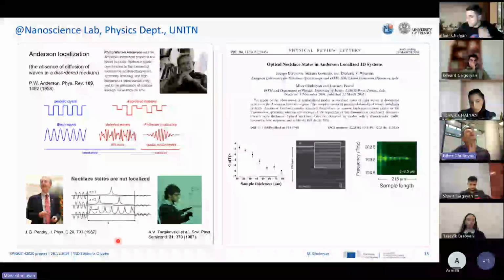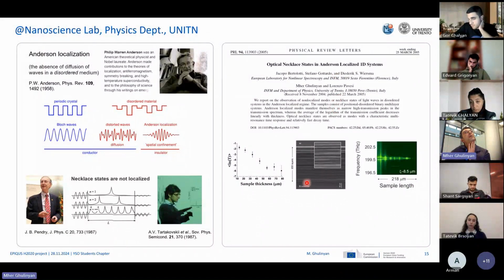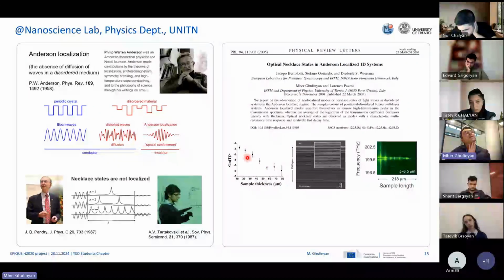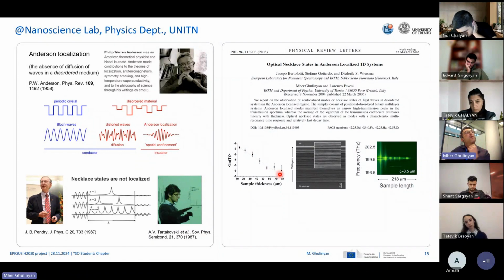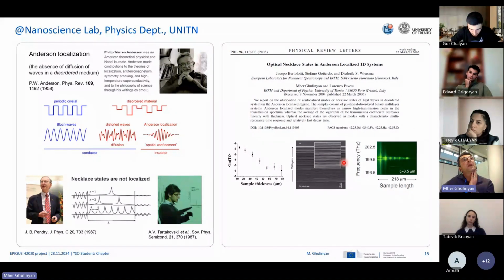And then we also made a random sequence of lambda/4 layers. They were no more periodic, and we totally randomized them. Making different thicknesses of the layers, we noticed that the transmission is exponentially dropping as the sample size increases, as predicted by the theory of Anderson localization. For light, it is also obvious, because these are waves. Then we noticed that at certain frequencies, occasionally we could get very high transmission. So instead of almost zero transmission for a very thick sample, you get almost one transmission.